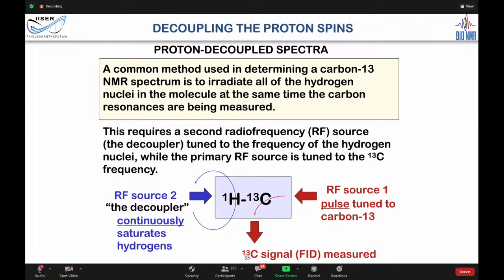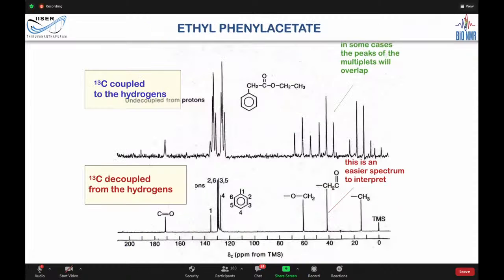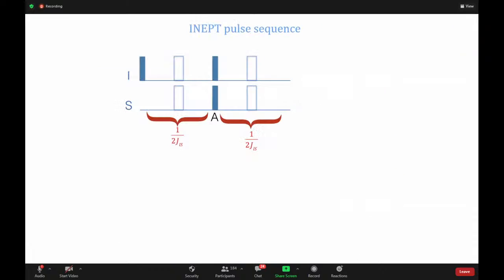You apply a 180-degree pulse on the protons. That means you are inverting the plus half and minus half states of the proton, interconverting them. So the 13C will not recognize which state it is coupled to, whether plus half or minus half. Then it comes into the original chemical shift position and will not be coupled. So when you do a 90-degree pulse and acquire the carbon-13, you do decoupling on the protons. 180, 180, it keeps doing. So you get no coupling, and such a neat spectrum.